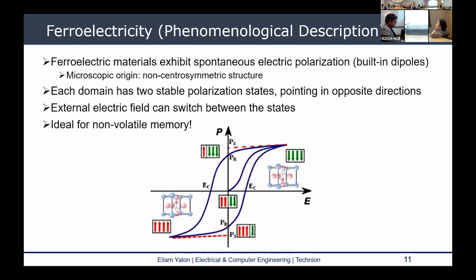switch those dipoles or domains. So the transition here is not abrupt because we have the domain structure. And then when we remove the bias, we have some remnant polarization, and that's what makes them ideal for non-volatile memories. Okay, so we have reversible switching between those polarization states. That's very briefly. And the origin of the phenomenon is some non-centrosymmetric structure of the material.